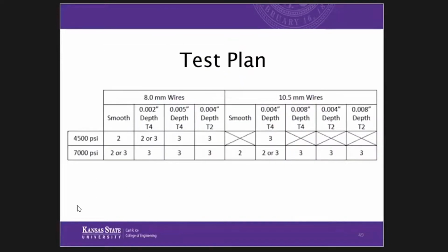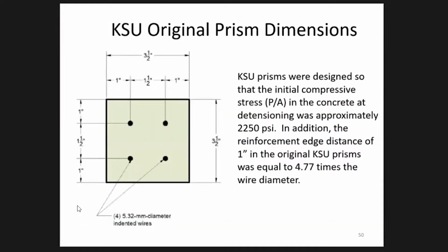In our test plan, for everything that was 8 millimeter wire, we detensioned at 4,500 PSI for half and 7,000 PSI for half. When we got up to 10.5 millimeter wire, if we want this to work in a railroad tie, it's going to take a higher release strength. Otherwise, our transfer length is too long. So most of our work was focused on 7,000 PSI release strength at detensioning, and one of the wires we looked at at 4,500. For the prisms, we used the same shape as K-State, but they had to be bigger to accommodate the wires. We provided the same P over A force. The original prism was 3.5 by 3.5 inches square. That had 28,000 pounds of force in a 3.5 by 3.5, which was about 2,250 PSI for our P over A force.